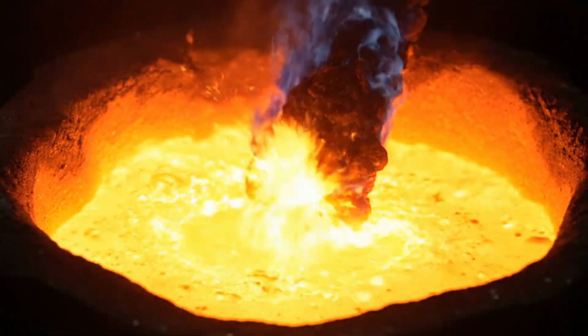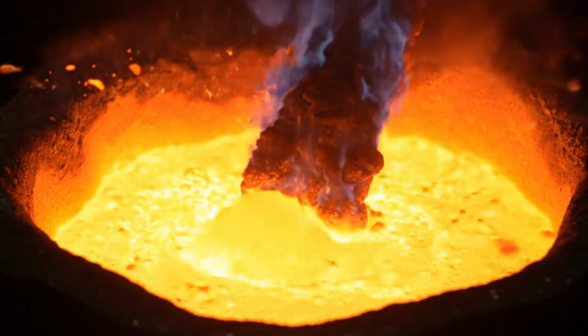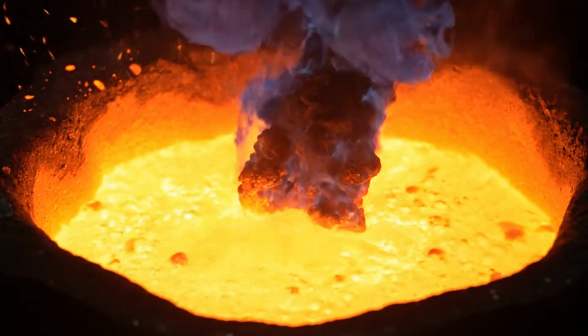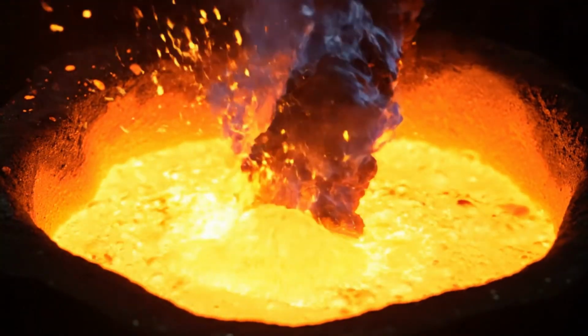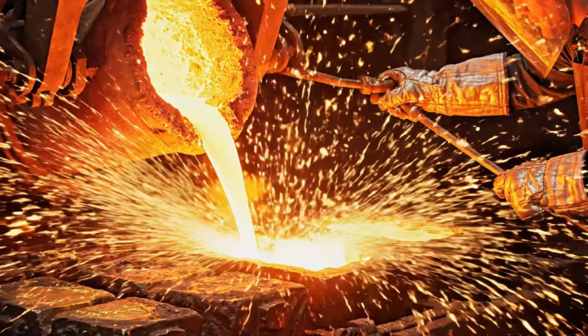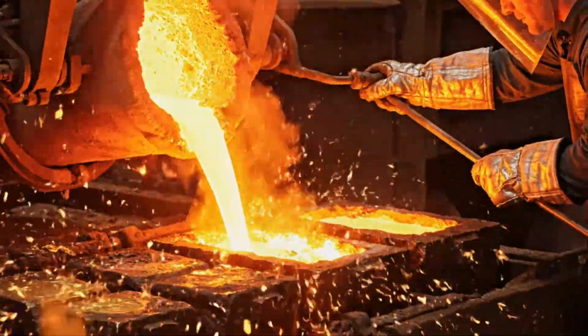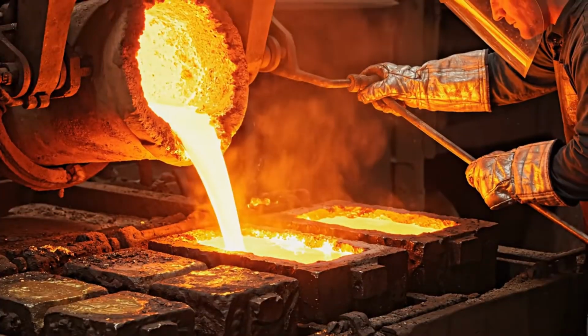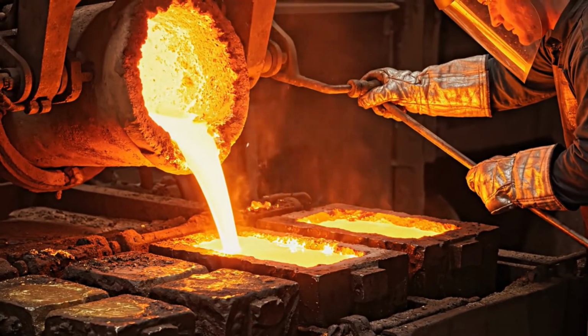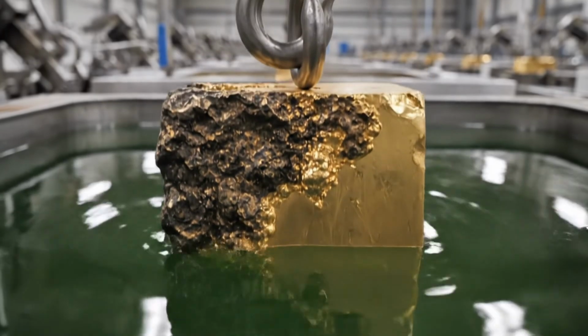The heat is intense and unforgiving, melting the sludge until the impurities burn away, leaving behind a glowing pool of pure molten potential. Workers in protective gear monitor the crucible, ensuring the liquid metal reaches the exact consistency required for the initial pour into rough molds. These rough bars are not yet pure.